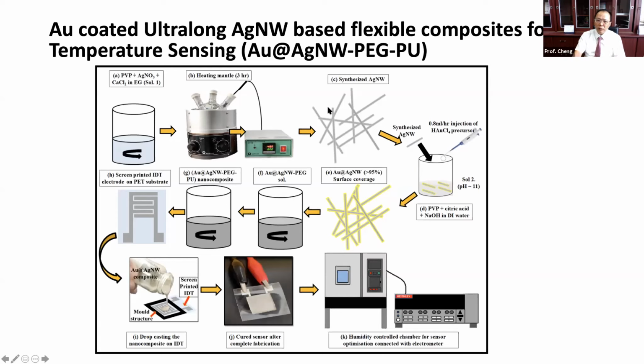So after we synthesize the silver nanowire, we also synthesize a gold surface coating on the silver nanowire. After we get this Au-coated silver nanowire, we mix it with the PEG. In this case, we use low molecular weight PEG, because for low molecular weight PEG, the Tg point is around human temperature. That will make this material have a phase change when the temperature changes. So we mix with the PEG, then we mix with the PU. PU is the matrix because it's a flexible substrate. Then this material will be very conductive.